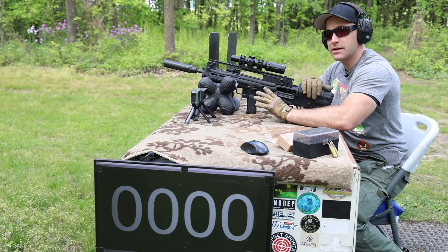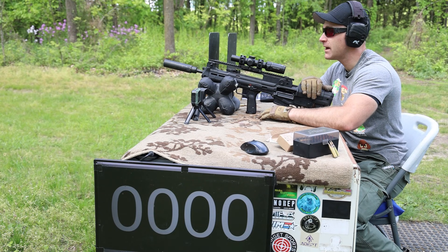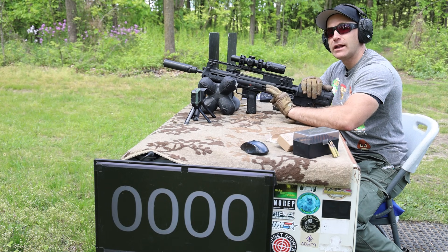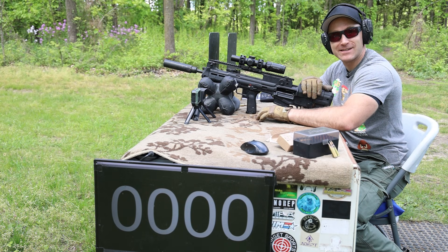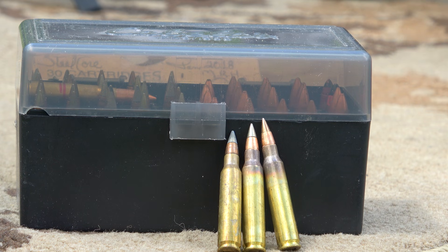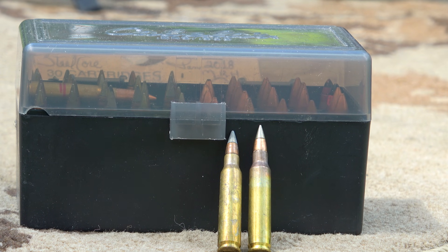For the workflow on this medium SRT sample, we're going to start off with our 16-inch M855A1 in 5.56 NATO. It's a 62-grain projectile with a copper core and a very large, hard steel arrowhead penetrating tip. Every time I've measured them, they're right around 59–60 on the Rockwell C scale — the variation allows 49–60 and they're always on the upper end. We'll take one shot from the 16-inch, and if it goes through, he wants us to put a soft backer behind it.